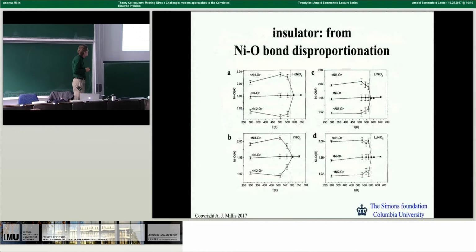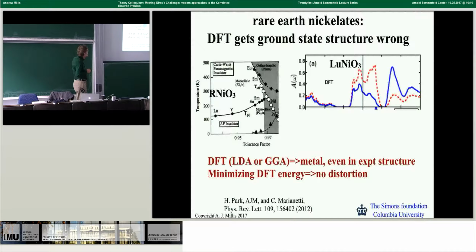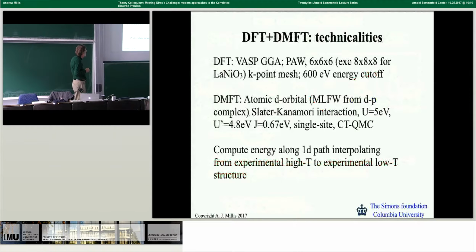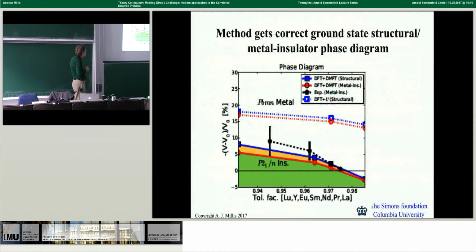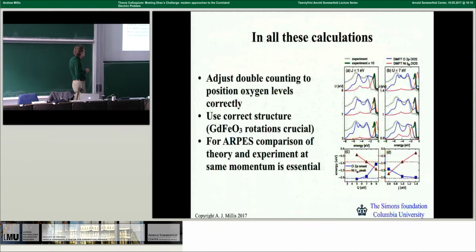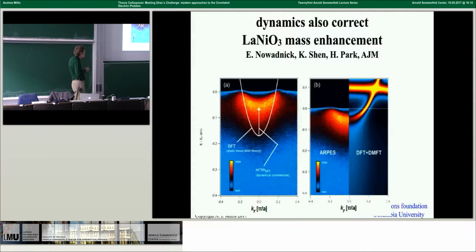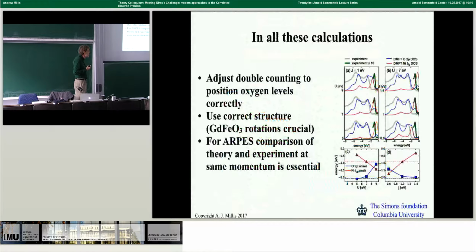All right. So you can play this same game with the rare earth nickelates. Because I'm running out of time, I'll just skip lightly over it and say that, again, we can apply this method. We can get much better agreement with experiment than standard methods for things like the pressure dependence of the metal insulator transition. We can account for the photoemission spectrum. But in all these calculations, we had to use empirical input. In particular, we used comparison to high energy photoemission experiments to determine the double counting correction and the Hund's coupling.